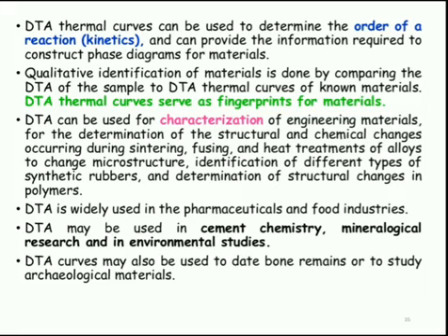In DTA, that is differential thermal analysis, a plot is made between the difference in temperature and temperature or time. Here, the shape and size of the peaks can give a large amount of information about the nature of the test sample. The endothermic peaks indicate significant changes in crystallinity or a fusion process. The broad endothermic peaks indicate a dehydration reaction, that is, physical changes give endothermic curves. We will discuss the characteristics of differential thermal analysis curves in detail in the next class.